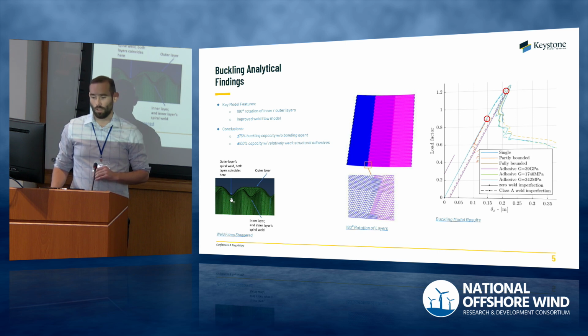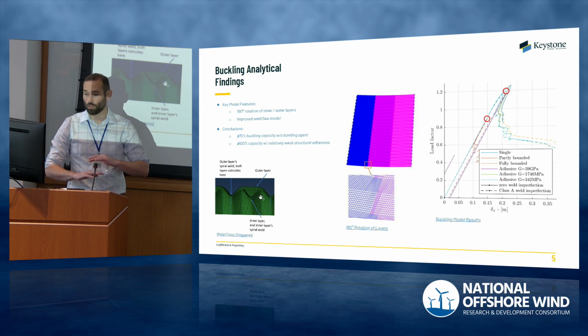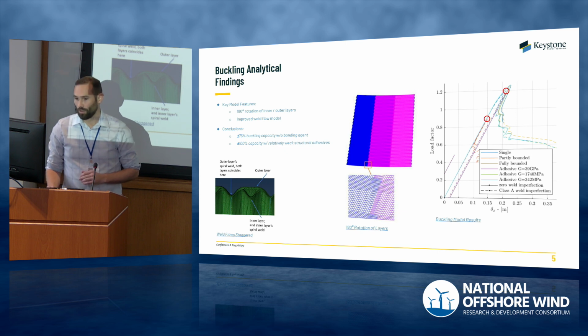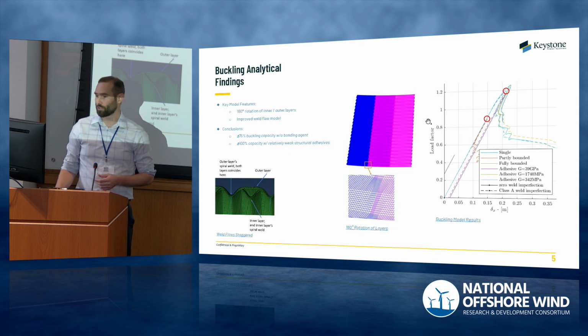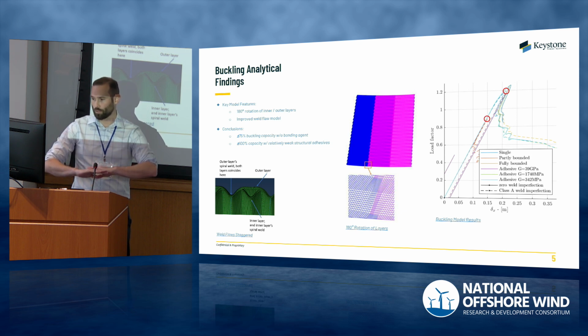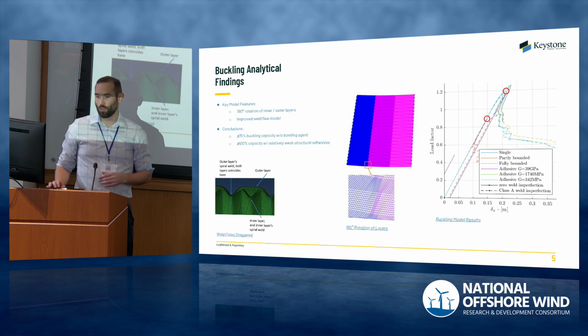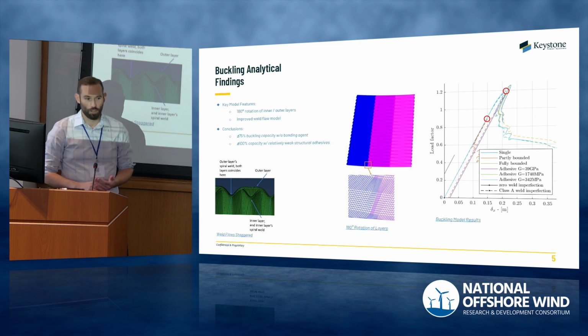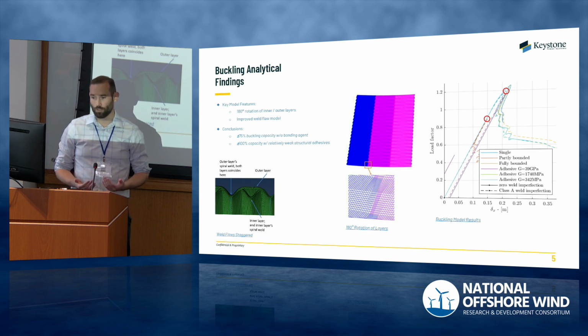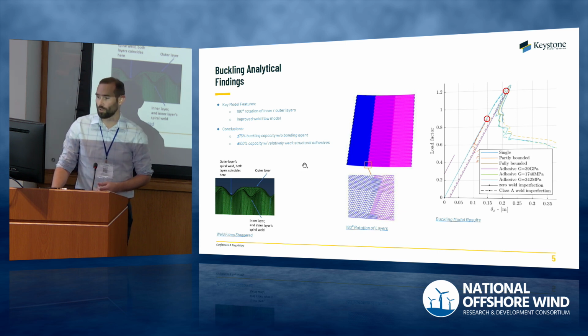And so what you'll get is two different layers with two different weld flaw geometries and conflicting buckling patterns, which would be a good thing, so they don't buckle simultaneously together. And so the output of this research is that just through helical welding of the plates like this, when benchmarked against a monolithic tower, you could expect about 75% of the buckling capacity. Adding in some structural adhesives, you can get up to 100%. And what the models are showing is that structural adhesive does not actually have to be all that strong, just some very moderate off-the-shelf type adhesives could achieve that.